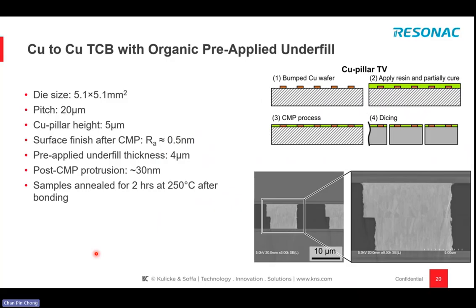All right, so this is the pre-apply. I will explain a little bit about this pre-apply underfill. This is basically the Resonac process. It's a spin-coated application process. It's a bump wafer. You apply a resin and partially cure it, you CMP process, and then you dice it. The die size here is about 5 millimeters, 20 micron pitch, copper pillar height about 5 microns, and then we have a 0.5 nanometer CMP after finish, and we apply an underfill thickness of about 4 microns. Then we do a little bit of protrusion of 30 nanometers, and then we anneal for about 2 hours at 250 after bonding.